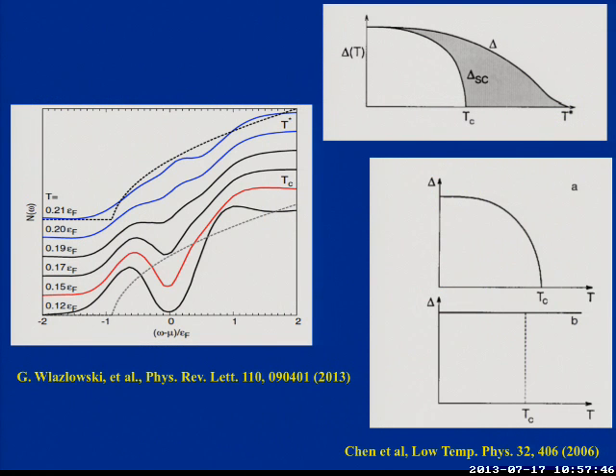If you have a BCS superconductor, the gap as a function of temperature behaves like this. If you go all the way to the other side, the gap basically is insensitive to the temperature because you have tightly bound molecules. You increase the temperature a bit, they're still tightly bound, and that's it. The unitary gas is somewhere in between, so you expect something like this. This is the gap everybody talks about. This is the actual gap you see. So this is the region where you see the pseudo gap.